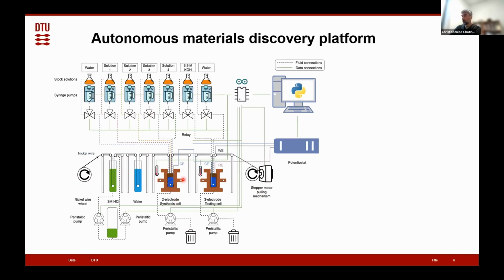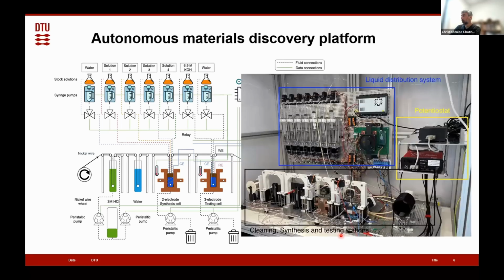So we can have different precursors at different ratios. The temperature can be controlled, the current density of the deposition or the overall profile of the deposition can be controlled. Finally, once this is completed, the chamber and the electrode is washed with water and transferred to the electrode testing cell where electrochemical testing takes place at industrially relevant conditions. Again, we can control the concentration of the electrolyte and we can control the temperature up to at least 80 degrees Celsius. So all the data are then analyzed automatically and fed into a machine learning algorithm that further guides the next experiment. This is how it looks in real life.